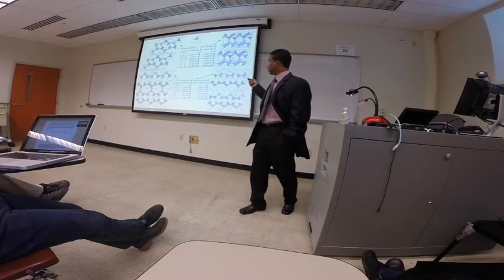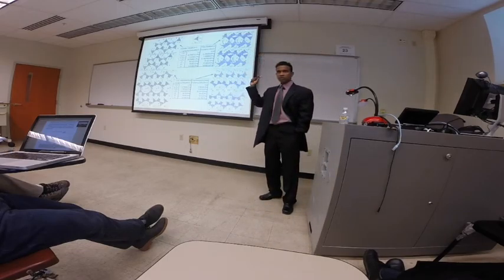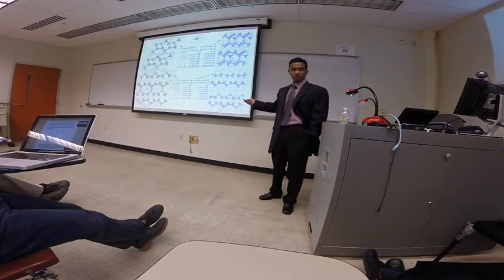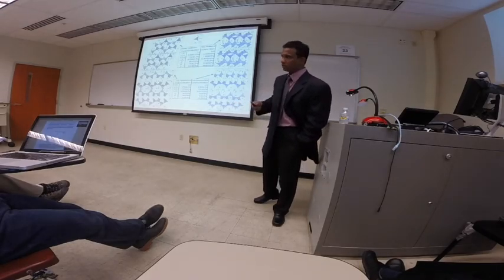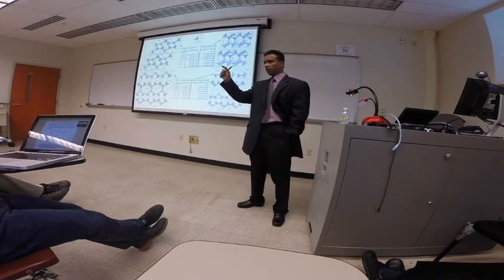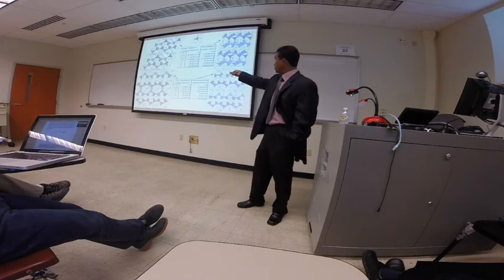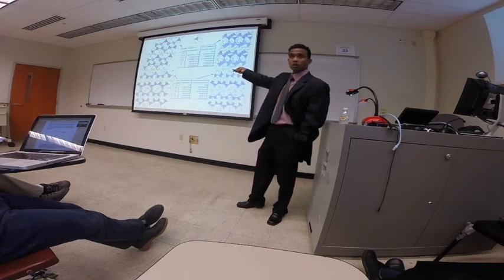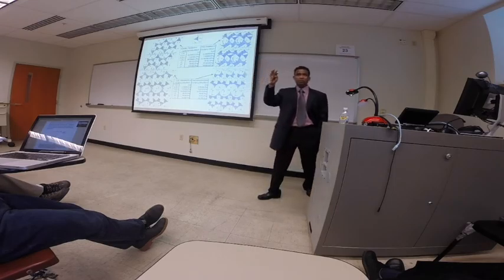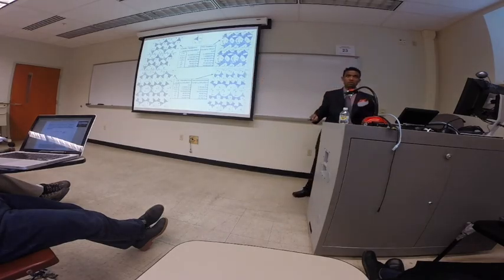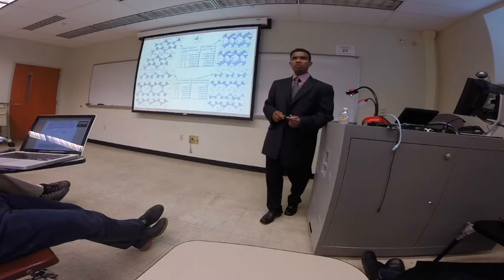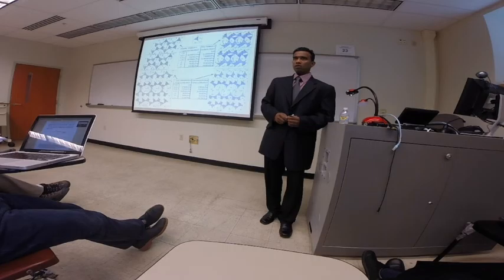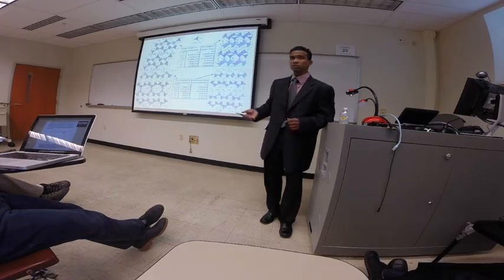Oh, when I was explaining the Richardson models, I said that CSH1 and CSH2, one is coming from the tobermorite family of crystals, and two is coming from the jennite family of crystals. Actually, the main reason is the broadest peak of normal cement relates to this interlayer distance somehow. That's how people picked up on that in the early 50s and 60s, that these might be prime candidates for cement models. So is there some mechanical property, something different, or is this a highly usable mechanical property? No, it's just the fact that you find that broad peak for that interlayer distance in XRD.